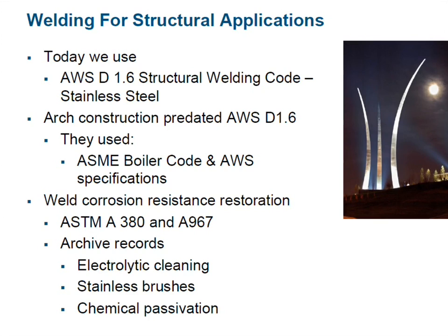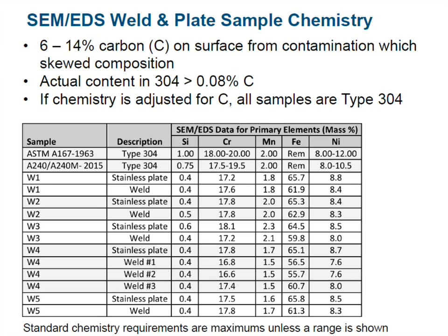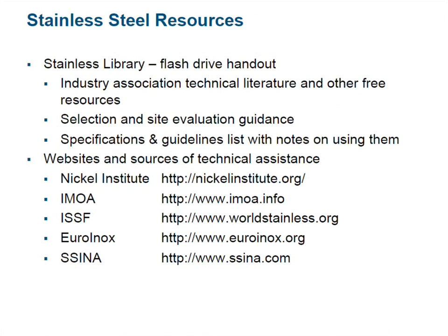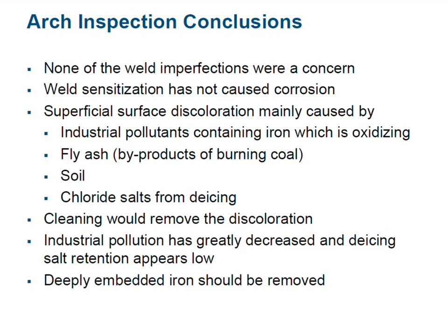The welds, we did find records of them, of exactly what was done, including the cleaning. It was done prior to AWS D1.6, a structural welding code, but it was all done to boiler code requirements at the time. So again, no concerns about what was done. We did confirm that it was all 304, including the weld material. I did want to point out that there are a lot of resources if you're working with stainless steel, including those on your flash drive, and some conclusions.